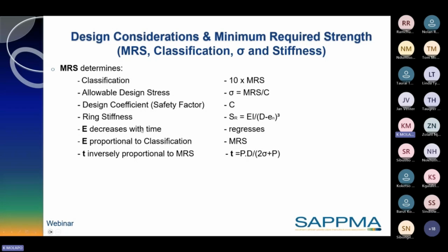The elastic modulus decreases with time. As we said, materials are the same as us human beings, in that with time they regress. And also E is proportional to the classification. So as the MRS decreases, E will also decrease. So T, which is what you will work out as your pipe thickness, is inversely proportional to MRS. So you calculate it using what they call the Barlow equation, where you cut a free body of a pipe, and you assume the wall is a thin section, and then you resolve your forces, and you should be able to work out the T, or the thickness, from the resulting equation.